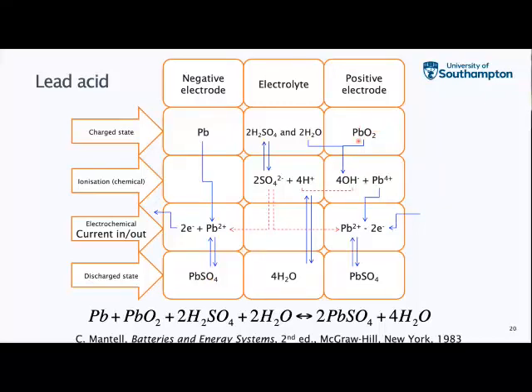At the positive electrode, that lead dioxide, again there's an ionization stage and there's a conversion from lead dioxide to lead 4 plus and hydroxide OH minus, and then conversion through an electrochemical route with lead 2 plus minus 2 electrons going to the lead sulfate. So effectively you're going from lead and lead dioxide to lead sulfate at both of the electrodes, and you're losing some of the free acid and generating water in the electrolyte. So there's a change in the composition of the electrolyte and the active species, and that gives you a corresponding voltage change for the system.